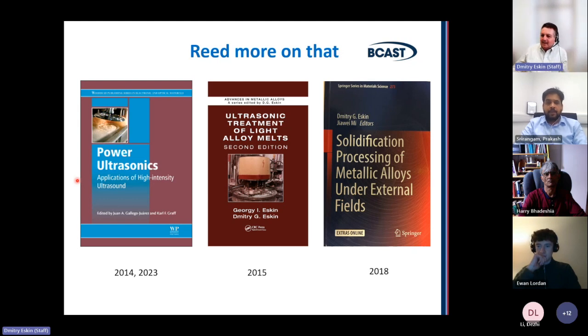I mean, in this book, there is a separate chapter on treating immiscible alloys, mostly like aluminium bismuth, aluminium lead, so mostly model alloys, but with good results. So it's absolutely definite that if you apply ultrasonic processing when you have these two immiscible liquid metals, one is as droplets in the matrix of another liquid metal. And then you apply ultrasonic processing at this stage, so the droplets become smaller and more evenly distributed. And then if you quickly solidify it, you will preserve this good distribution.